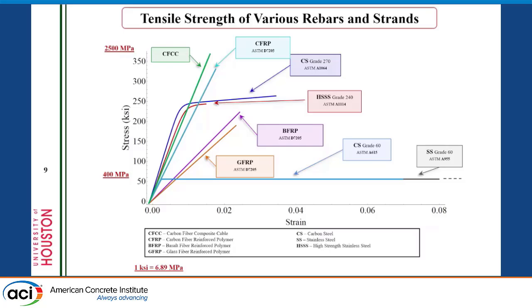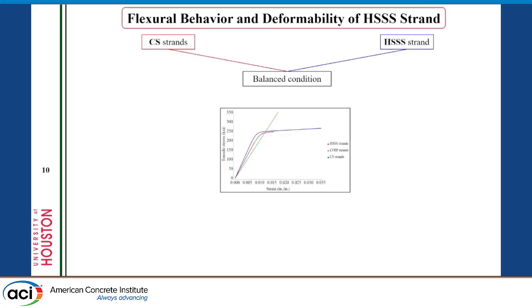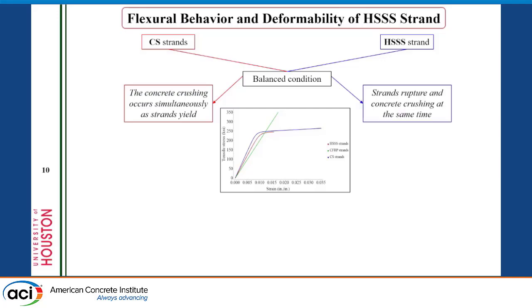And that's the question that we want to address if we have this kind of lower ductility, because usually when we design our bridges and beams, we have our balance condition. It's when the concrete crushes at the same time as the strand yields, and in this case we have tension or compression control. But for the stainless steel, our balance condition is when the strand ruptures, because we have the yielding, but between the yielding and the ultimate there is very low strain reserve. So our balance condition is when the strand ruptures at the same time as the concrete crushing.